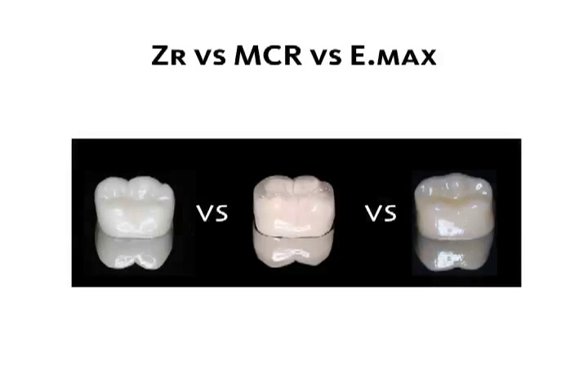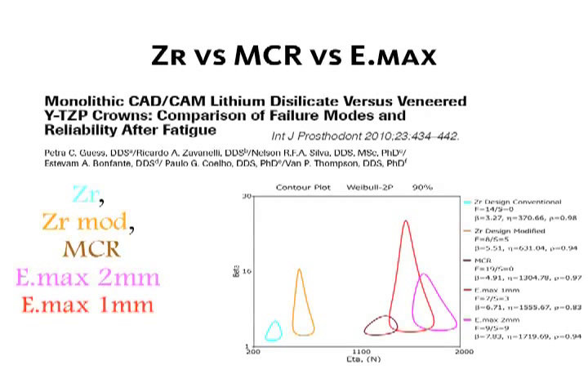The next comparison involved full contour or monolithic lithium disilicate E.max crowns. The results showed that either 2 mm or 1 mm thickness E.max crowns should behave like metal ceramics in terms of reliability, as you can see by the overlap between these contours on the right-hand side of the graphic.